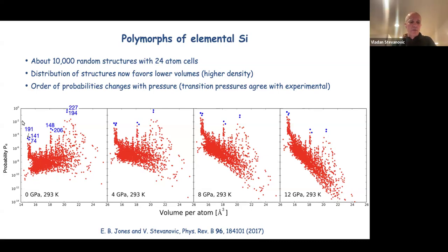So this is the probability distribution, again calculated at room temperature for elemental silicon. The first thing that is noticeable is that the ground state diamond structure of silicon appears as the highest probability, as one would expect, because it's a ground state structure with low-temperature Boltzmann factors, so it's going to dominate the probability. But then the distribution now tilts to the left, not to the right as in silicon carbide and graphite. This shows that there are really no biases in our random sampling towards less dense or more dense structures. This tilting of the potential energy surface towards lower or higher density is physical, and I'll come back to that later.